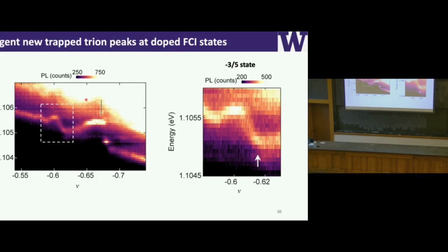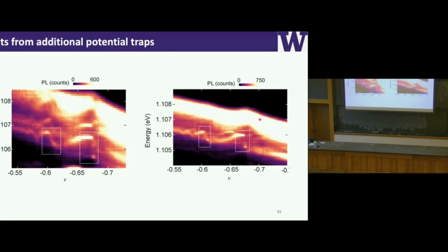Then we can also look at the 3/5 state again, right? When we dope the 3/5 state, you will see there's a little plateau in terms of energies. Then a little bright feature appears as we dope it, okay? All right, and this data can be observed in many different traps. So here are two different examples, right? Let's focus on the right one. For example, the 2/3 state, we see a little plateau feature with a bright feature when we dope it. And the 3/5, again, we have a little plateau feature, and when I dope the 3/5 state, a bright feature shows up. Okay. So this little bright feature we call the fractional charge trion state.